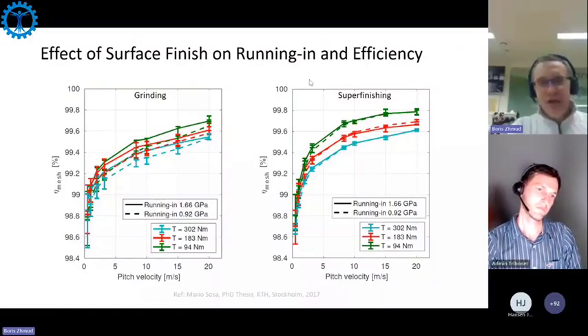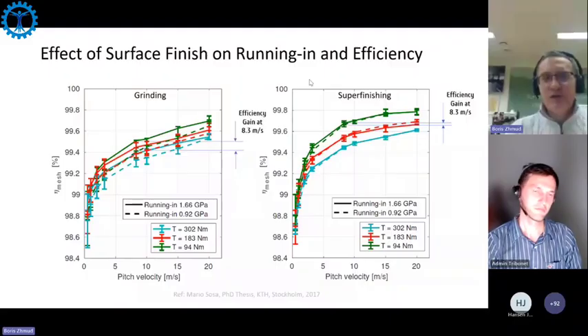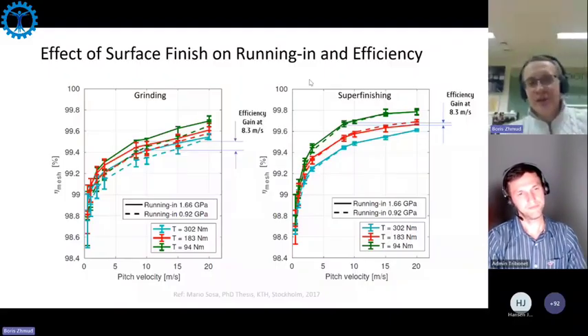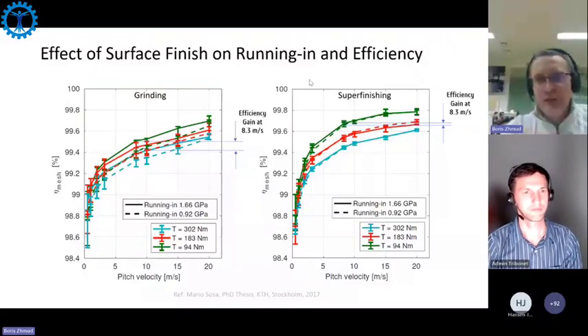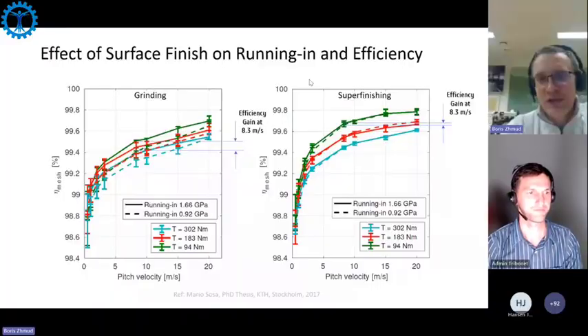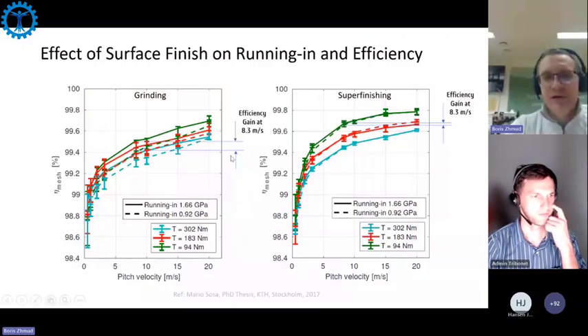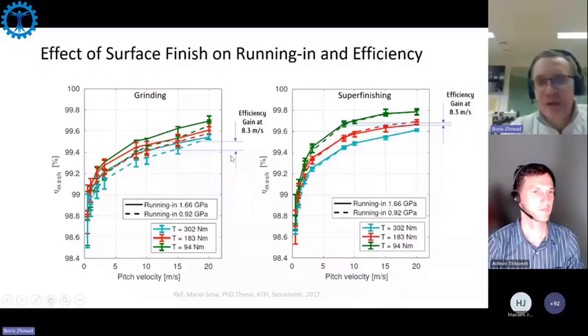If you look at the data showing efficiency versus pitch line velocity for ground gears and super finished gears, you will see that the improvement in efficiency due to running in is bigger for ground gears than for super finished gears. For super finished gears, efficiency is almost unchanged before and after running in. For ground gears, efficiency significantly increases after the running in process.